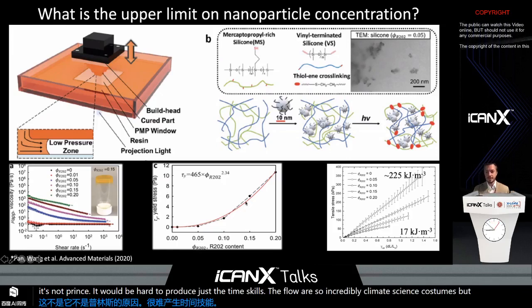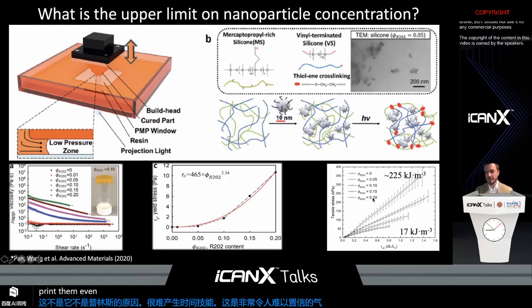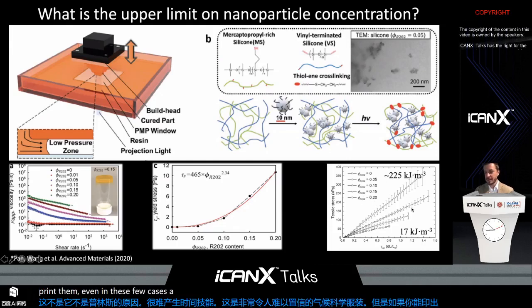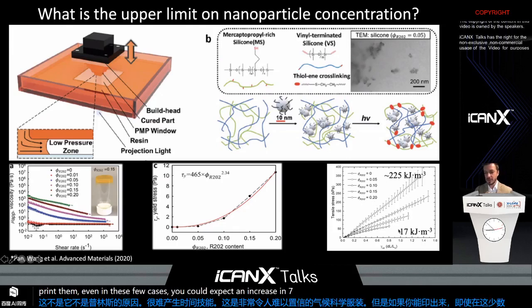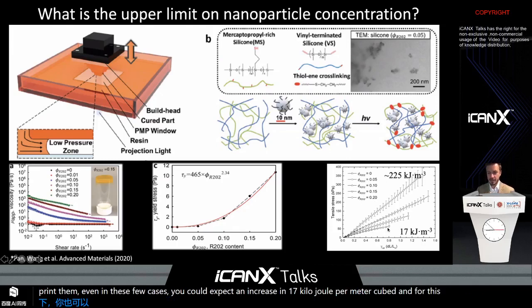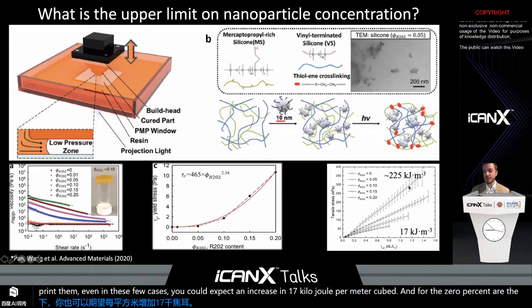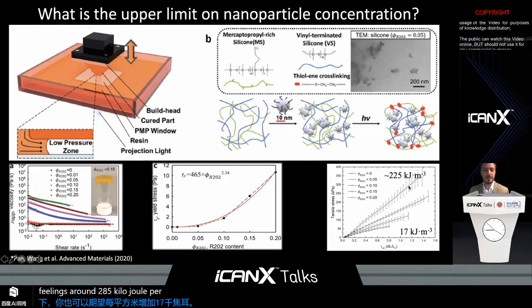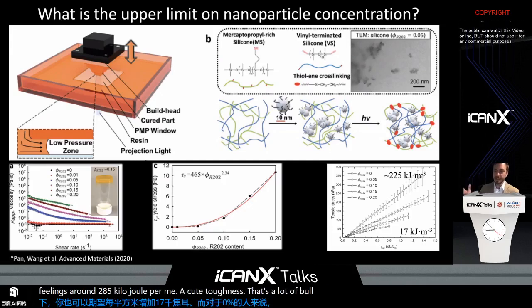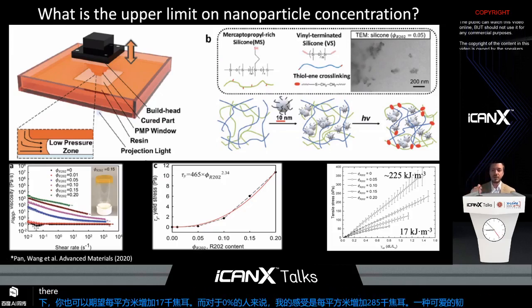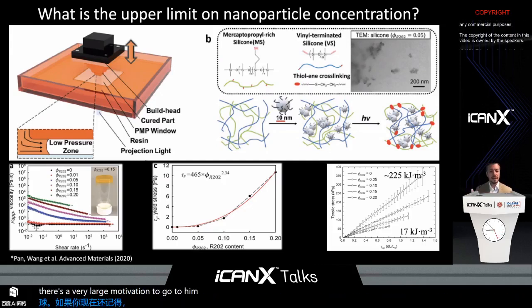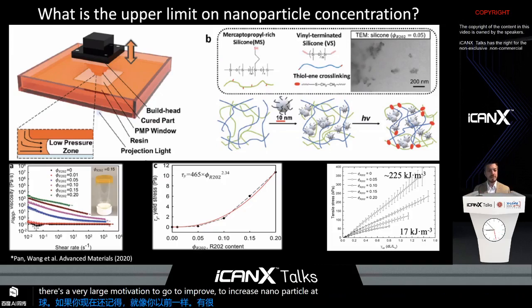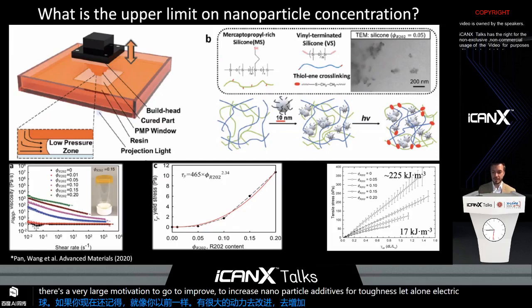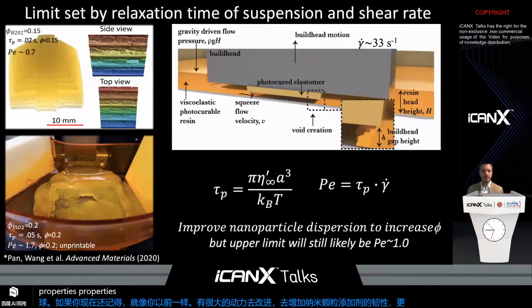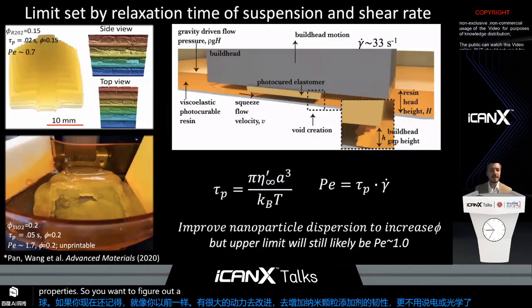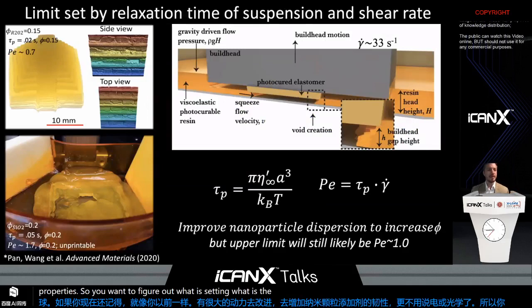But if you could print them, even in these fumed silica cases, you could expect an increase from around 17 kilojoules per meter cubed for the 0% nanoparticle filling to around 225 kilojoules per meter cubed toughness. That's a lot of bowling balls, if you remember my analogy earlier. So there's a large motivation to be able to increase nanoparticle additives for toughness, let alone electrical or optical properties. So we wanted to figure out what is the ultimate limit here.